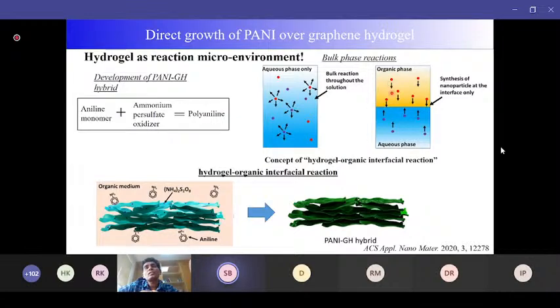In the aqueous organic interfacial reaction, people use it to grow nanomaterials. Instead of using a purely aqueous phase, why do people use the organic and aqueous phases? Because there are two reactants, and they are separated in two different phases, so they cannot immediately mix to form nanomaterials. Whereas in the aqueous phase, their mobility and diffusivity is so large that the reaction is immediate. But in the organic and aqueous phases, the reactants diffuse through the interface slowly, and this slow process can give rise to the growth of uniform nanostructures.